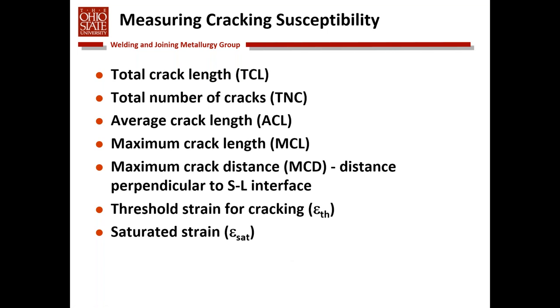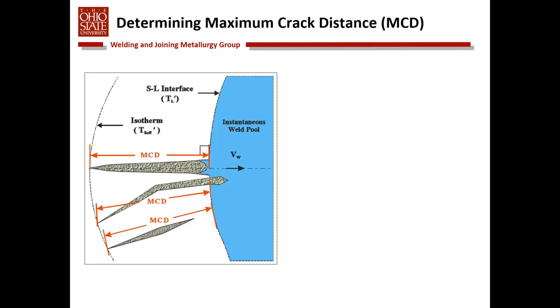The measurement and quantification of cracking susceptibility is a little bit complicated. These are all the different methods for measuring cracking susceptibility. Total crack length is widely used. Maximum crack length and maximum crack distance are also widely used. You can also determine a threshold strain for cracking, or what we call a saturated strain, where the cracking basically levels out at high strain levels.